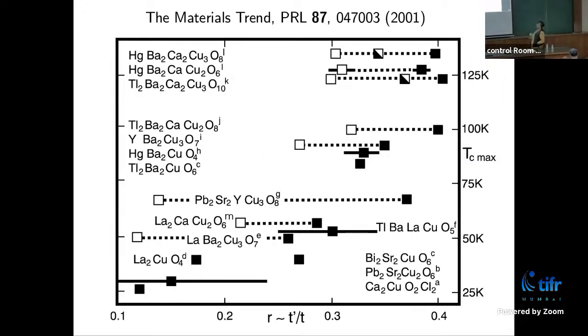And long back, in 2001, we had this paper, and 20 years down the line, using the same idea, people published another paper in PRL, and we had to write a comment, and they gave some reply. Anyway, what we found is that it is not just the case for lanthanum and mercury. We did this calculation for almost all known hole doped high TC cuprates. I will not get into the details, it was a very painful calculation. This is more like a semi-empirical plot, because this R parameter is our calculation, and we did not calculate the TC. It's just the measured TC at optimal doping.